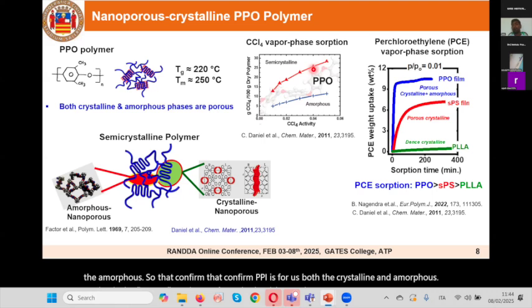For a clear-cut confirmation, we also studied this. For comparison, we took three different polymers: PPO, SPS, and PLLA. For these studies, we chose a different vapor molecule, perchloroethylene (PCE), and we studied the sorption at a very low activity, 0.01. You can see the weight uptake. PPO shows the highest sorption, followed by SPS, and very low or negligible in PLLA. So this confirms that PPO is definitely porous in both crystalline and amorphous phases, and SPS is only crystalline porous.